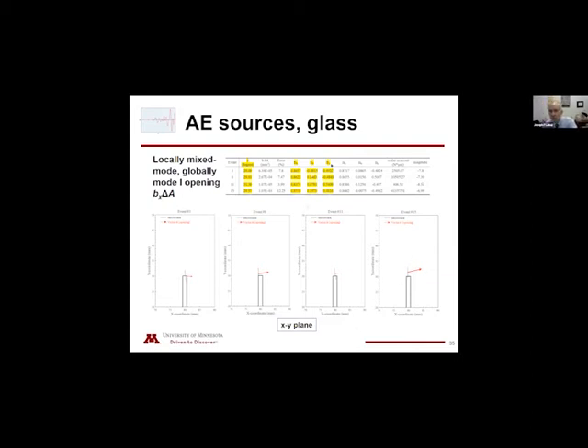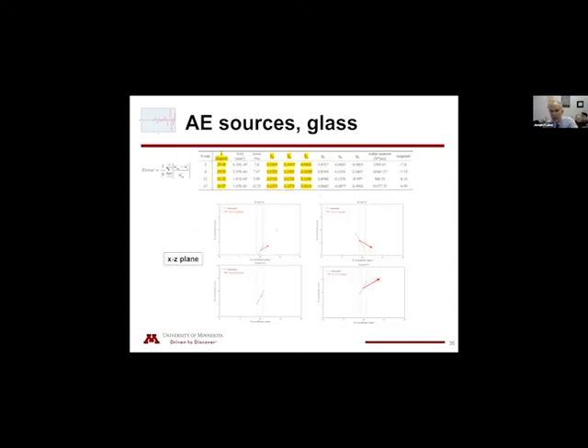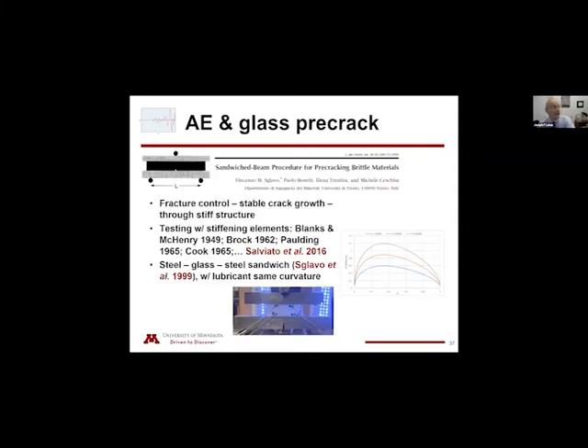It's interesting to look at the Z component. So now we'll look down on the beam. This is in the XZ plane. So again, the opening that we like to see, but there is a significant component out of plane, and that's shown by these numbers. These two are going in the opposite direction, but then you see these other two that are in the same direction of Z. Okay, finally, because I'm out of time, it's difficult to control, as that test indicated.